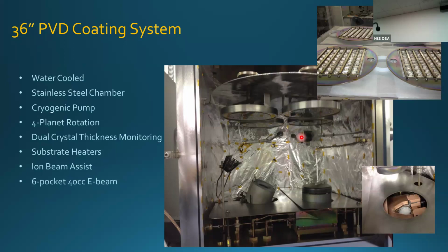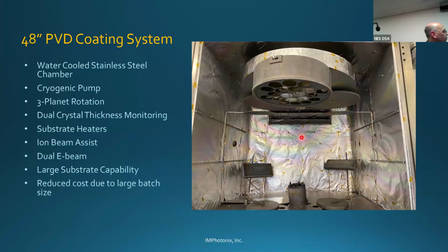Again, we use substrate heaters to bring the substrates up to temperature, and an ion beam to assist in the film formation. For more cost-critical work, where batch size is important, we can scale that up to larger sizes. We can go to longer coatings with dual E-beams, so we can evaporate more material for more layers and longer deposition coatings, and we can handle larger substrates. But it's the same technology, just scaled up to a larger system.